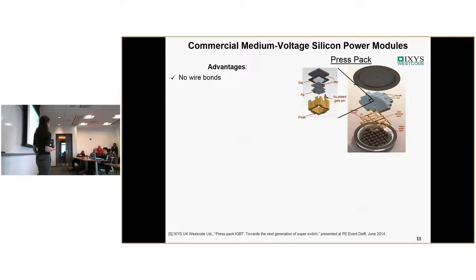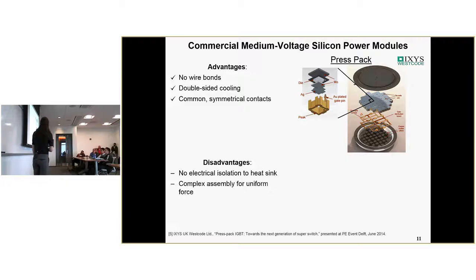Advantages: no wire bonds, so higher energy absorption during faults. Double-sided cooling, so you're cooling from both the bottom and top, whereas before I showed you that you only cool from the bottom. Symmetrical contacts to all the die, so you avoid some of the asymmetry issues. Disadvantages, though: it's not isolated from the heatsink. In order to make sure that those contacts are in good contact with all of those die cells, you need a very complex structure outside to make sure that the force is uniformly distributed. Otherwise, if it's distributed at an angle, then maybe you're contacting some die better than others. And that's not good for cooling purposes as well as the electrical connection.